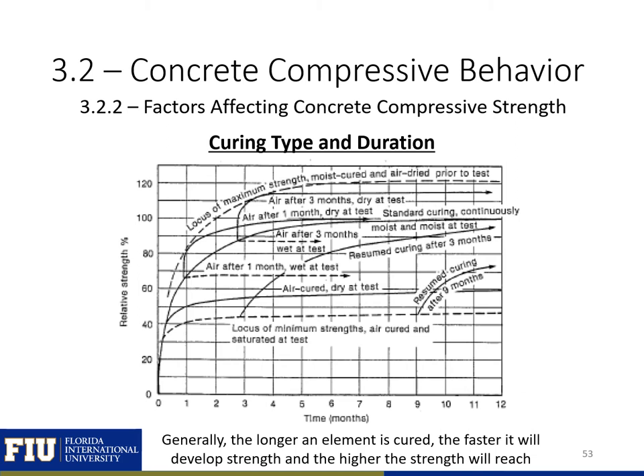The curing type and duration will have an impact on the early age strength, but will generally have a minimal impact on the ultimate strength. This plot shows the relative strength versus time for concrete cured using different methods with differing amounts of time. Proper curing will improve early age strength, and if water is reintroduced to the concrete at any time during its life, a more rapid strength gain will generally occur. The long-term strength will usually converge at about the same value, though. Note that this plot does not consider the use of SCMs. Initial curing conditions are much more critical for concrete containing SCMs.